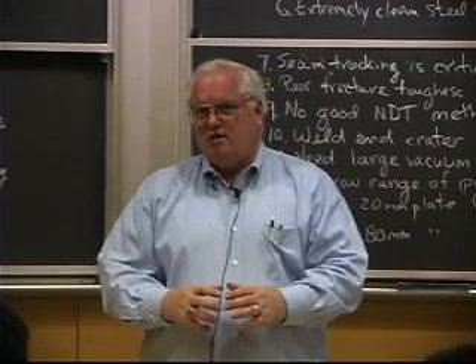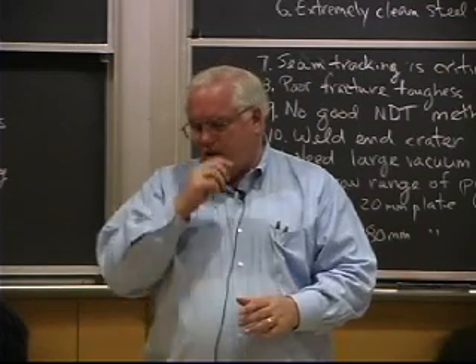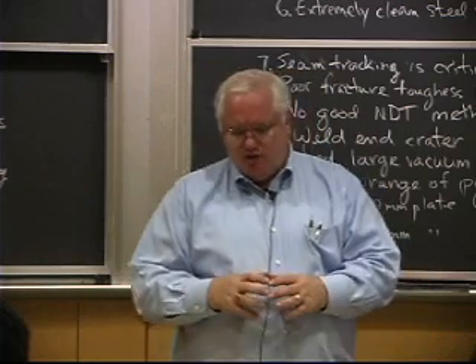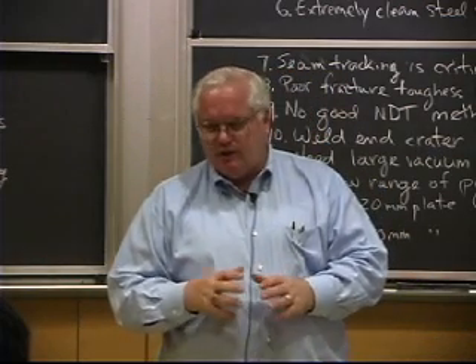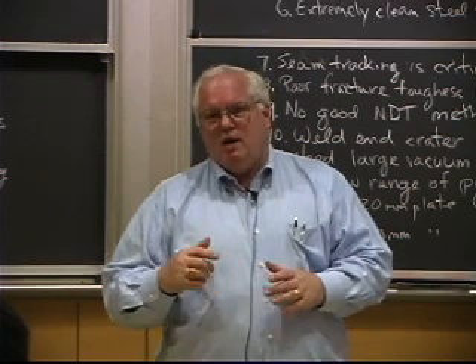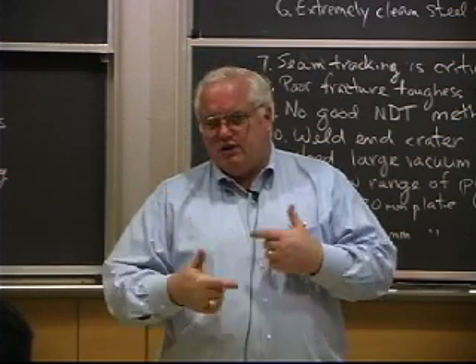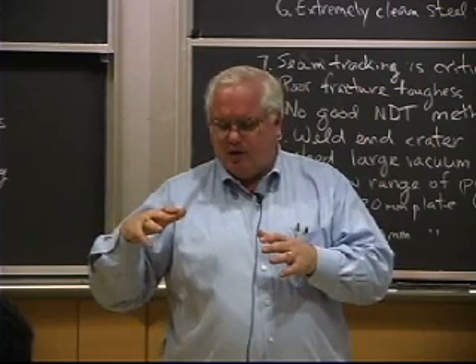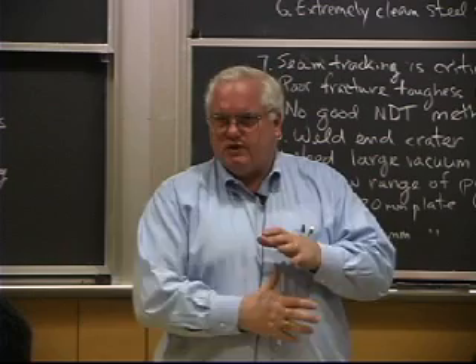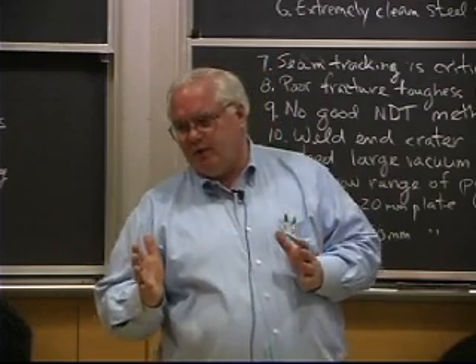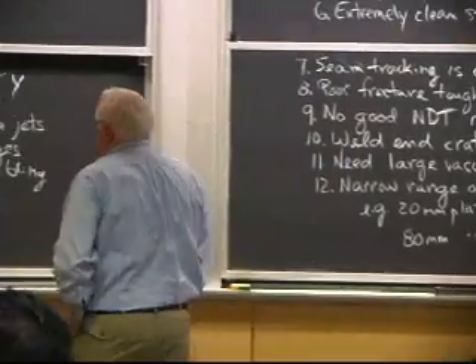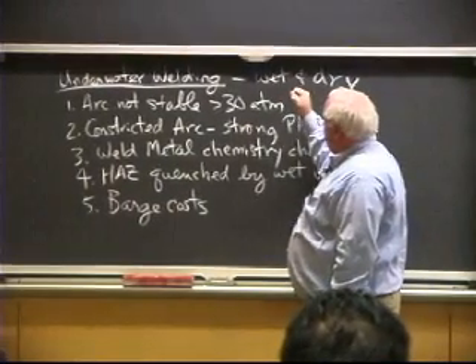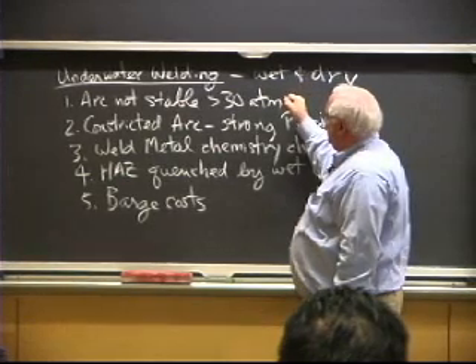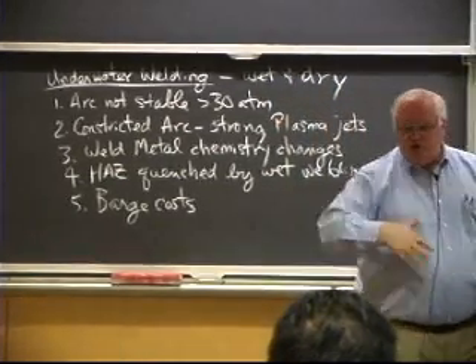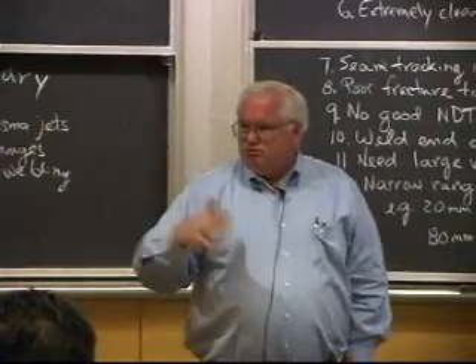So initially, as you squeeze an arc, the arc constricts, and the percent ionization in the arc increases, and the whole thing gets hotter, and you have stronger plasma jets, which is the next thing. But if you keep on doing that above about 30 atmospheres, you eventually get into places where if you have any type of perturbation, that high pressure basically swamps out the arc and just shoves the gas away, okay? The convection currents on the outside become unstable. So it becomes unstable whether you're in a gas or whether you're surrounded by water. But you can strike an arc underwater because essentially you're generating this gas, and the gas is pushing the water back. And you can do it. You can do it to several hundred feet wet.